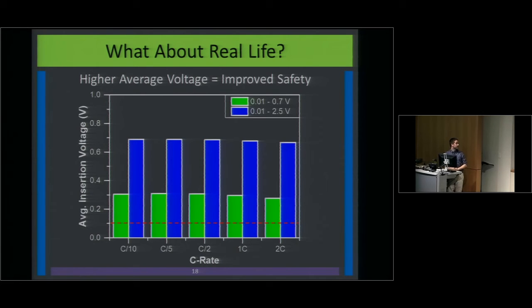Now we get to the fun part, which is what would this look like in a real battery? I mentioned before the fires that can be caused by graphite having too low of a lithium insertion potential. Graphite's potential is this red line here. You can see for my battery, the average lithium insertion potentials are much higher — in the lower voltage range it's about 0.3, and in the upper voltage range it's about 0.7. Both of these are significantly higher than the lithium plus redox couple, so we won't get those needle-like dendrites, and we won't get the terrible flames we saw before.